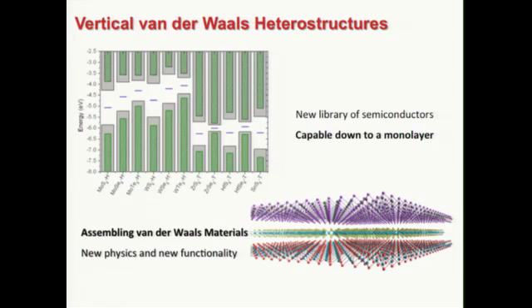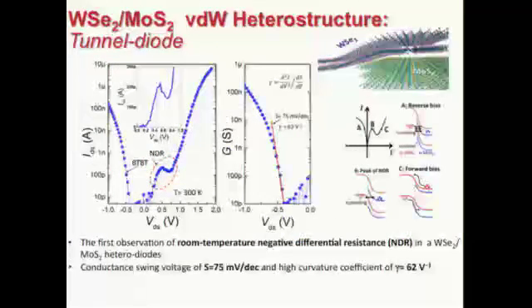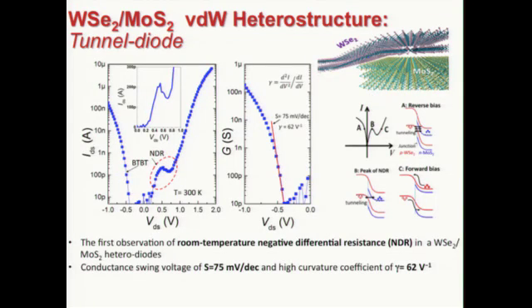Because here, the advantage is that we actually have a very sharp interface. We don't have defects or dangling bonds on the interface. So technically it's very clean, and that can basically solve this problem. So we tried a simple example. We tried a tungsten selenide molybdenum disulfide device. It's a PN junction. So MoS2 is N-type, and tungsten selenide is typically a P-type semiconductor.